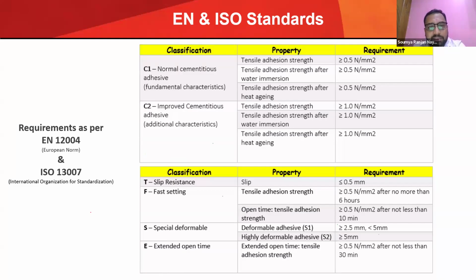But these are the symbols summarized here. C1 is normal cementitious, C2 is improved cementitious, and there are some properties that must be there in tile adhesives, like slip resistance. Slip resistance means when you apply tiles, they will not slip. When you apply a tile on a vertical wall, it will not slip. If it slips, it will be below 0.5 mm. That's the typical nature of a thixotropic material.